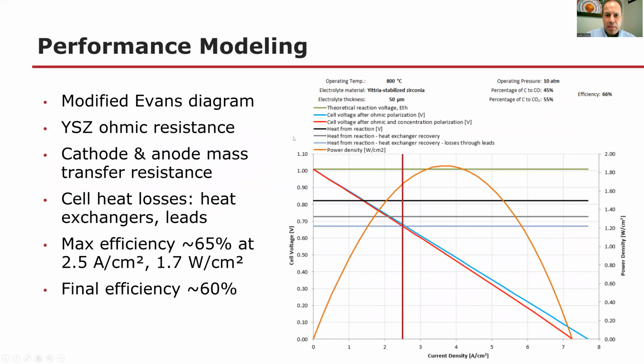So in terms of performance modeling, this modified Evans diagram shows that we have a theoretical voltage around 1 volt at 10 atmospheres of pressure. So as we go to higher current density through the zirconia, that resistance generates heat, which reduces the energy available. This time we're flipped relative to the metal production. Our voltage, electrical energy that we take out has to be less than the heat that's generated by the reaction in order to maintain thermal balance without providing external heat, which we don't want to do.